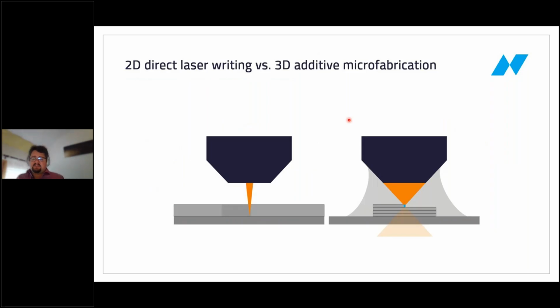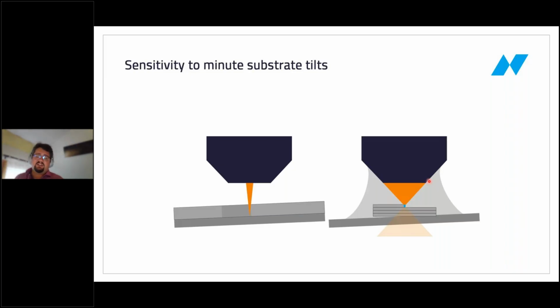So this was already hinted at before in the talk by Severin, but I want to show this a little more detailed here because it's very relevant to how we implemented it. If you do 2D lithography, the laser beam is almost parallel, and you illuminate your material, and usually you can penetrate all the way in. Whereas in our case, we are printing layer by layer and we have a very tight Z confinement. If we now work with a slightly tilted substrate, as is unfortunately hard to avoid, even if you build all the parts, but especially if you have customer-specific holders, it's very hard to get to this precision that we saw before. 0.0-something degrees is very hard to achieve mechanically. This can then lead, as you can see here, either to sinking into the substrate or not being properly in contact with the substrate.